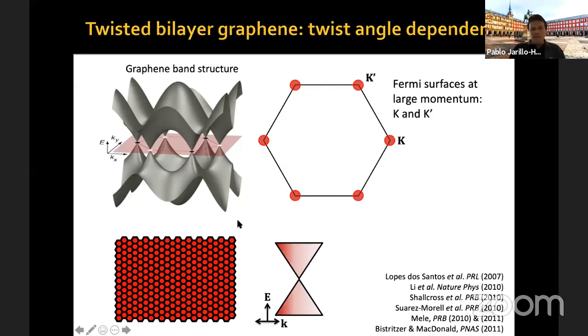Now, if you look in momentum space, you have this hexagonal Brillouin zone, and if you put your Fermi energy at a finite value in graphene, such as here, then you get these Fermi disks at the so-called K and K prime points. Now, what happens if you put one sheet of graphene on top of another sheet of graphene?